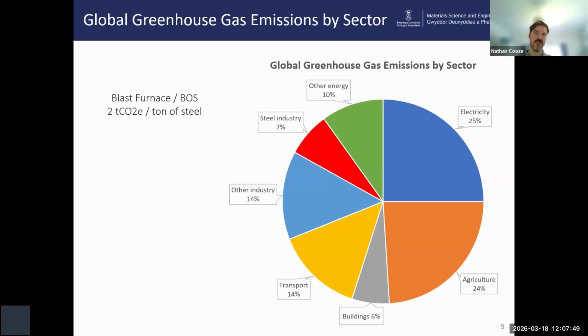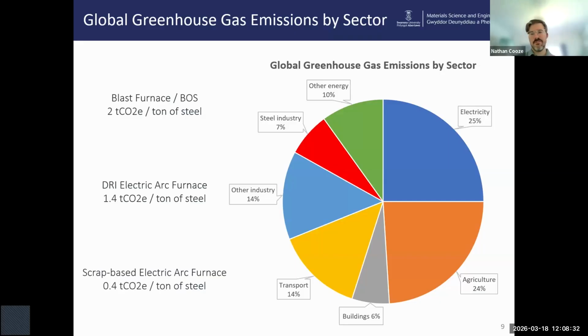So in blast furnace or traditional basic oxygen steelmaking, for example, the carbon dioxide emissions are typically 2 tons of carbon dioxide per ton of steel. With the natural gas direct reduction of iron or DRI process with electric arc furnace steelmaking, these emissions are typically reduced to 1.4 tons of carbon dioxide per ton of steel. If we were to use a scrap-based electric arc furnace steelmaking process, the emissions are typically reduced a lot further to 0.4 tons of carbon dioxide per ton of steel. And further advantages of arc furnaces are reduced cost of steel production and reduced energy requirements. So there is a need really for fossil-free steel in order to help achieve net zero. But how is all this relevant to hydrogen?